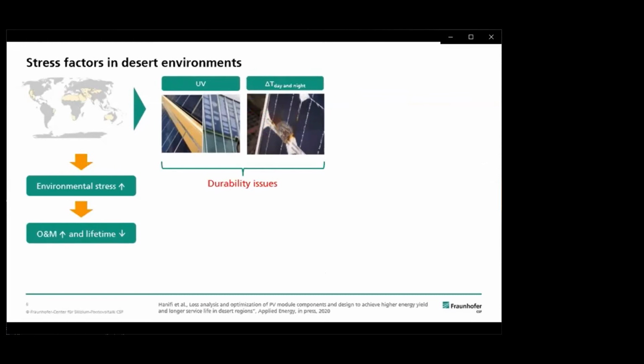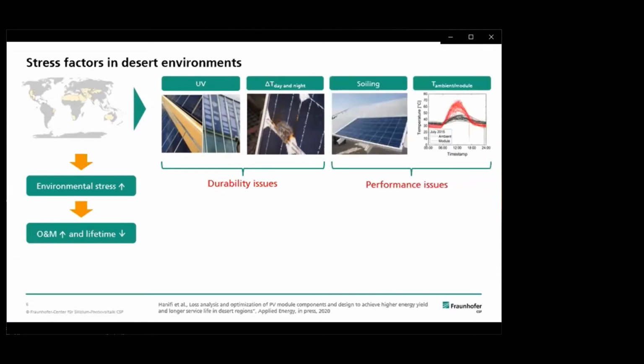So first, starting with durability issues, you can see some example degradation modes caused by UV on the left side, which is, for example, discoloration of the backsheets or delamination of the polymers. And on the other hand, you can also get a formation of hotspots because of breakage of tabs between the solar cells. We don't only have durability issues, we also have performance issues, which are mainly due to high temperatures on the one hand, which you can see on the right, and also due to soiling, the deposition of dust and dirt on the PV modules blocking the sunlight.